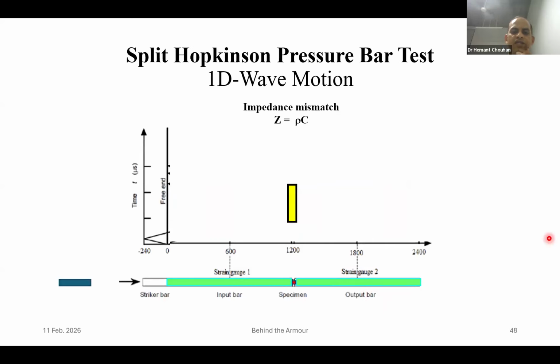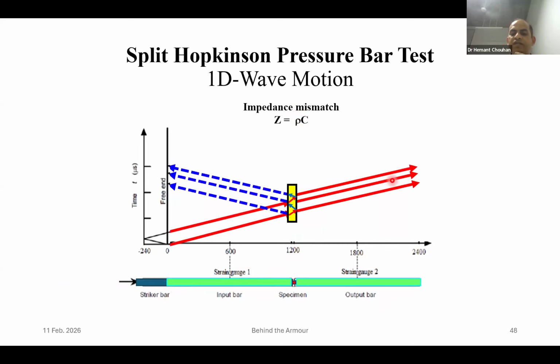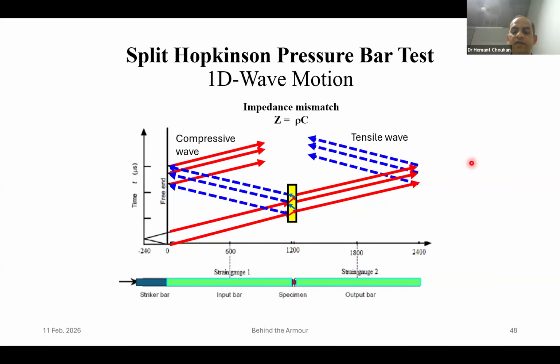Now, this is the typical mechanism of a split Hopkinson bar, wherein a striker hits a homogeneous material. As an outcome of that, a compressive wave travels through this particular bar, and we have placed the specimen at the center of it. So, depending on impedance mismatch, which is a function of density times velocity of sound in a material, the reverberations of this stress wave will happen and we will have a reflected and a transmitted wave, and these three waves, that is the incident, the reflected and the transmitted, will tell us the material properties.